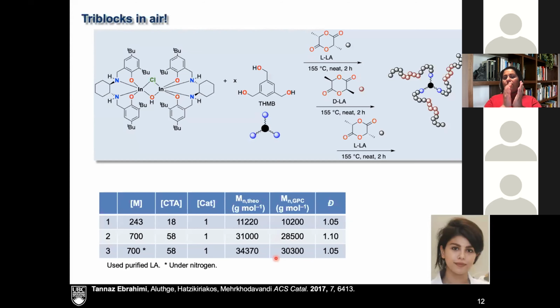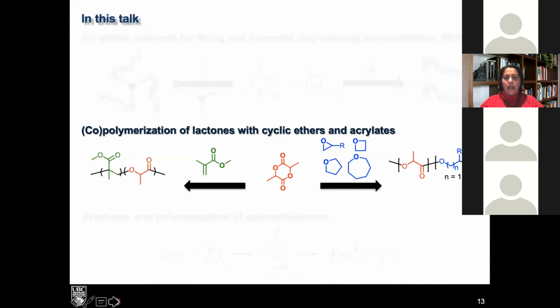So what we were able to do was, because we were using indium, because it's air stable, because it's water stable, we don't have to go through a purification. We can do this reaction in air, which was really cool. And there was no solvent required. So we were quite excited about this reaction. But that's just the background for the indium chemistry.